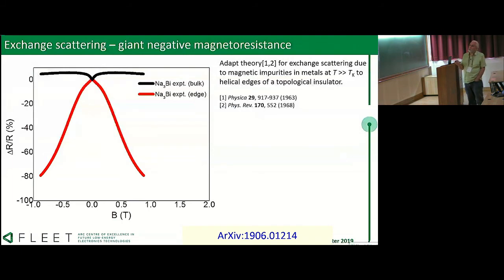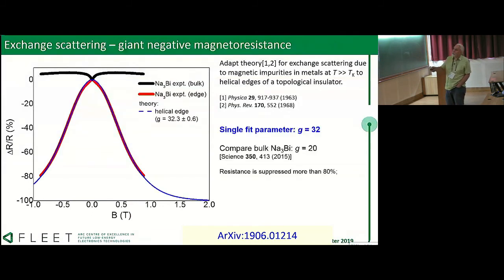So this was actually worked out in the 60s. It was worked out with a slight mistake in the calculation in 1963, and then that was corrected in 1968. If we just adapt that theory, we can fit our data. There's a single fit parameter. The only thing that's in here is the G factor. Essentially what we're doing is we're Zeeman splitting these local moments. Backscattering becomes inelastic, and so it's suppressed by magnetic field.